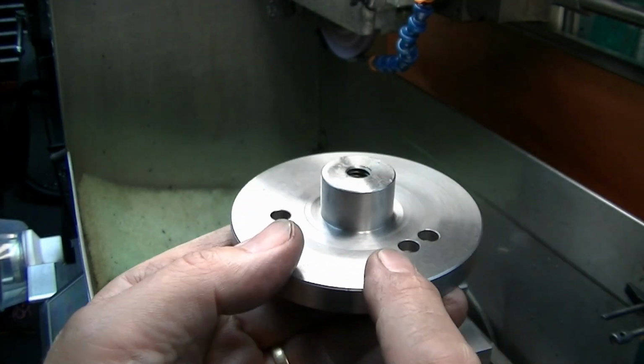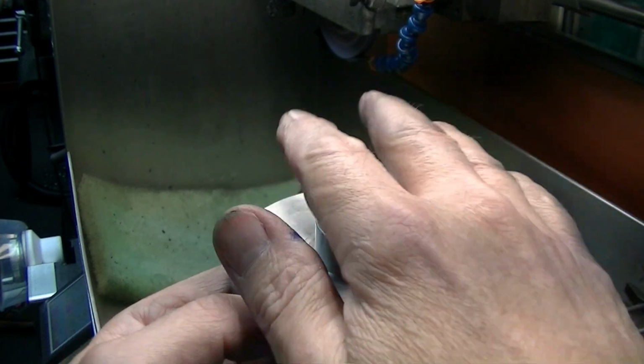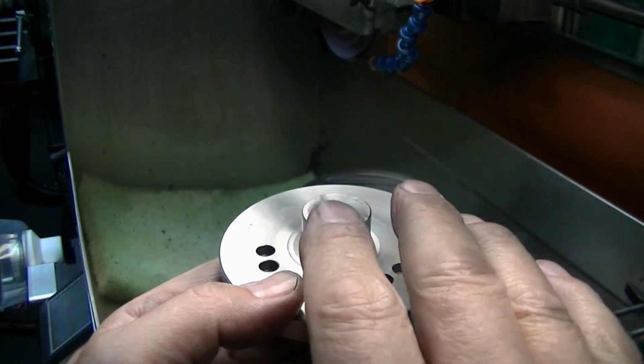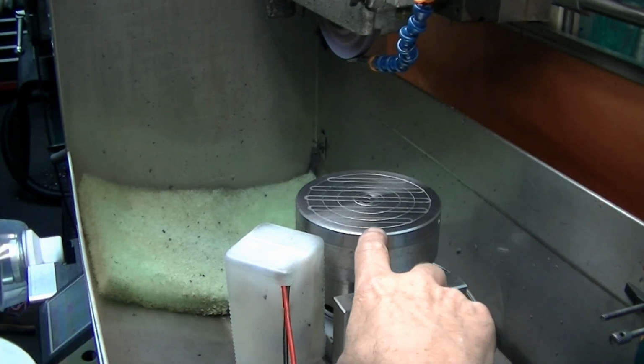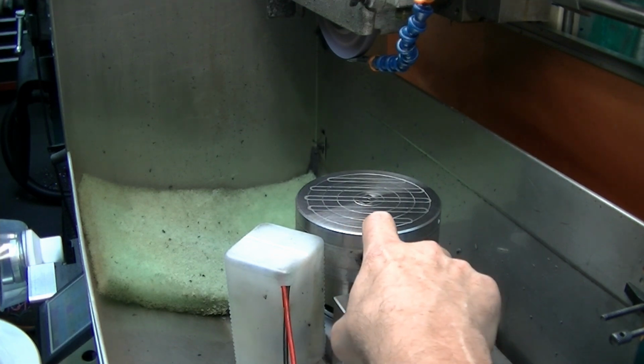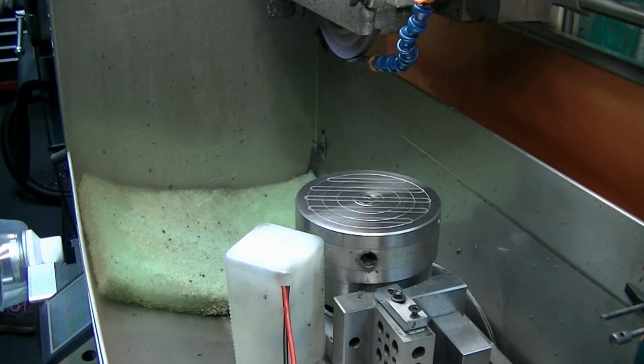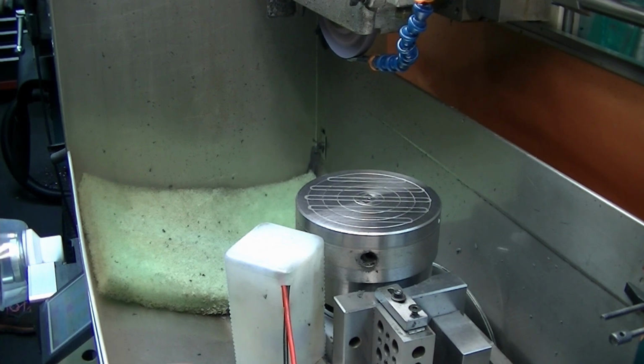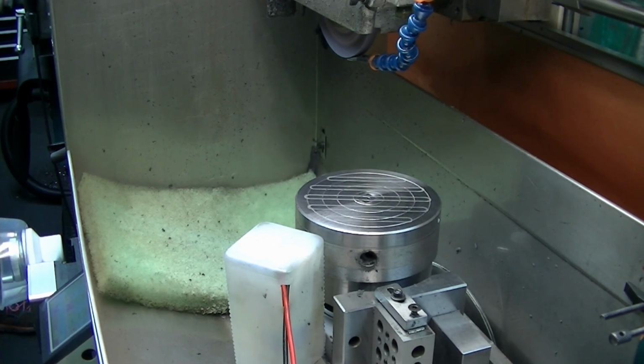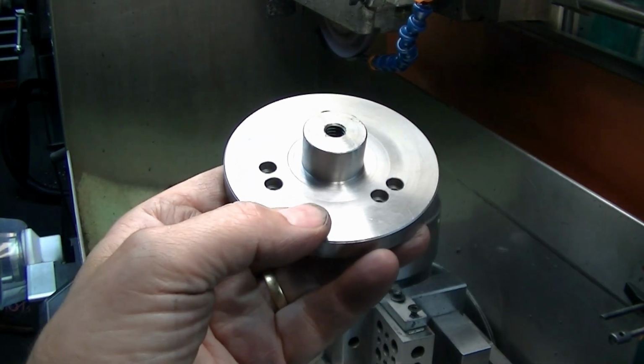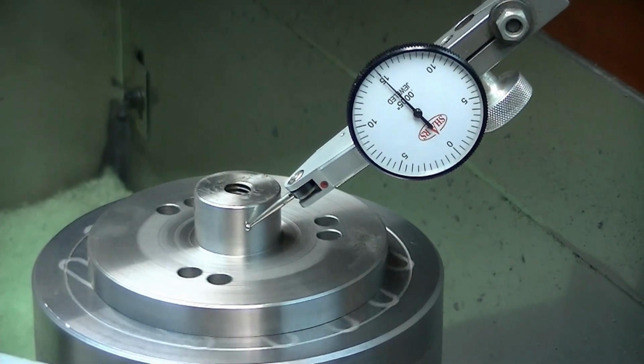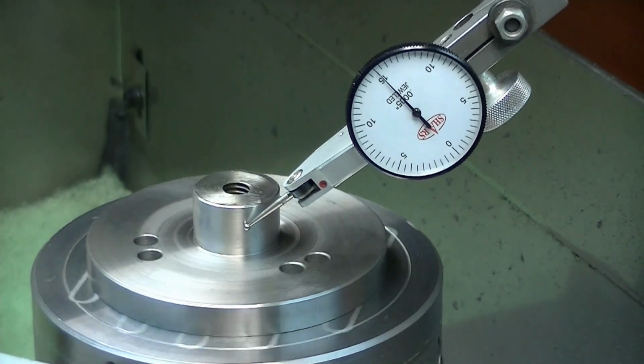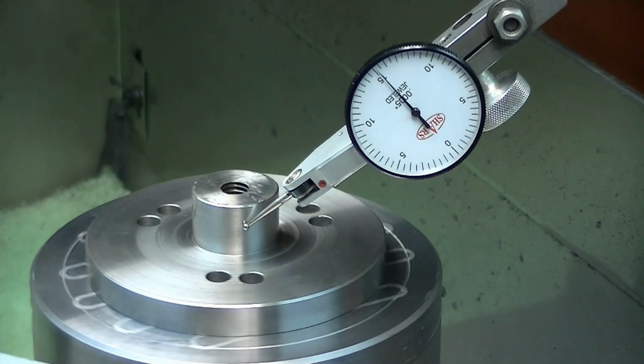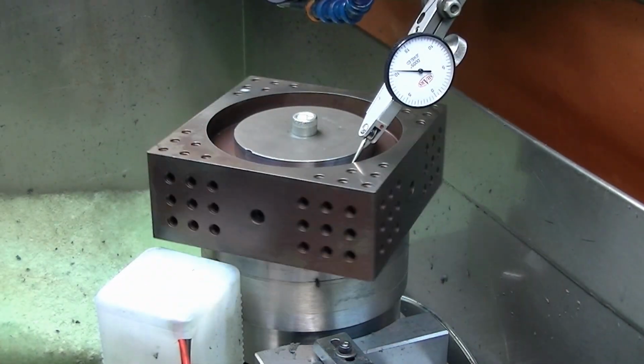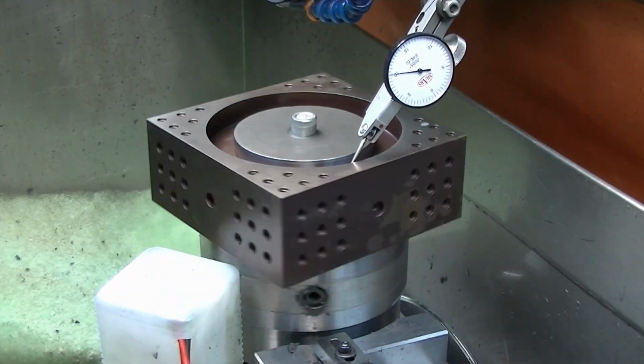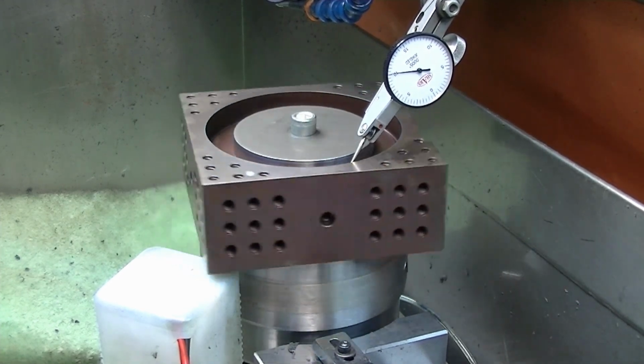So I'm going to put this on the magnetic chuck and then use a cover plate inside to just physically, mechanically hold the part touching this outside band. So basically clamping it to the face of the magnetic chuck, even though the magnetic flux is not running through the part itself. It's simply holding this on. So I've tapped this in to run within a thousandth or so, which is severe overkill. Doesn't need to be that good. Here you can see I have that indicated in within a few thousandths, which is plenty, and I will grind that upper face.